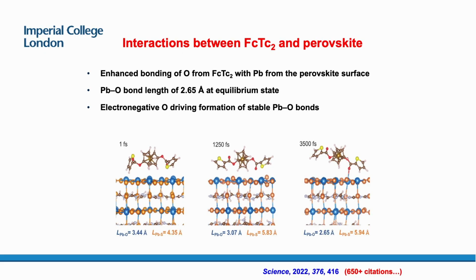And so we looked at, why is this happening? What's happening on the surface? And as I say, there's lots of details. You can have a look at the publication. It's been very popular in the field. We've already got over 500, 600 citations in 2 years. So it's really galvanized the area into thinking, how can we manipulate these layers? And we think there's the combination of the ferrocene, the movement of electron density, but also the perovskite surface. You can see these lead atoms are now being passivated, what we call passivated. They're being bound to by the oxygen atoms in our compounds, and that's helping with the degradation.